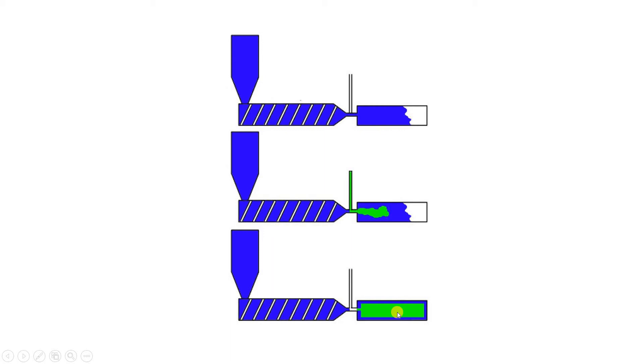In gas assist molding, plastic material is melted with the help of an extruder barrel and injected into the mold cavities like a regular injection molding process, but only up to 70 to 80% of the mold volume is captured this way. When the plastic melt contacts the mold wall and begins to solidify, nitrogen gas is injected through strategically designed gas channels, providing gas pressure near the wall. The plastic material is then pushed into the mold extremities and becomes rigid, and finally the molded part is ejected like in regular injection molding.